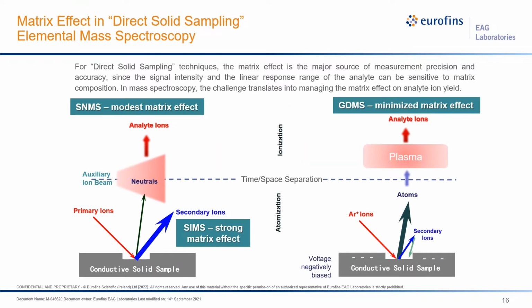For trace analysis, direct solid sampling techniques are preferred because they provide easy sample preparation and low contamination risk. However, it does not come without expense. In the direct solid sampling technique, the matrix effect is a major source of measurement precision and accuracy issues, since the signal intensity and the linear response range of the analyte can be sensitive to matrix composition. In mass spectroscopy, the challenge translates into managing the matrix effect on analyte ion yield.